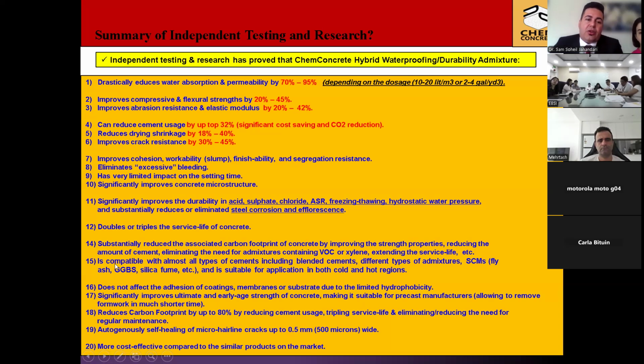It is compatible with almost all types of other cements, including blended cements, different types of admixtures, and supplementary cementitious materials like fly ash, GGBS, silica fume, and it's also suitable for application in both cold and warm regions. It doesn't affect the adhesion of coatings or membranes or substrate due to the limited hydrophobicity.